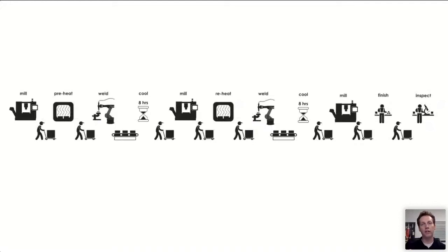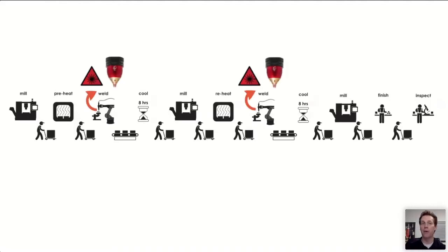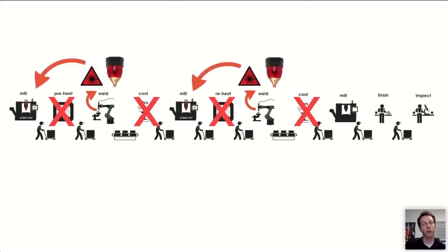And so as we look at it with new eyes and say, okay, we can now do additive, we can do it within an architecture that's flexible. Let's see what makes the most sense. First off, let's replace the conventional welding with a laser-based weld. What that will allow us to do is skip the preheat and cool down cycles. By skipping those, then we say, okay, where are the other processes? Well, you got multiple processes in a milling machine. Well, let's take that laser-based deposition, let's put it in the milling machine itself, so that then your common denominator is milling machines. You no longer need the robotic line.